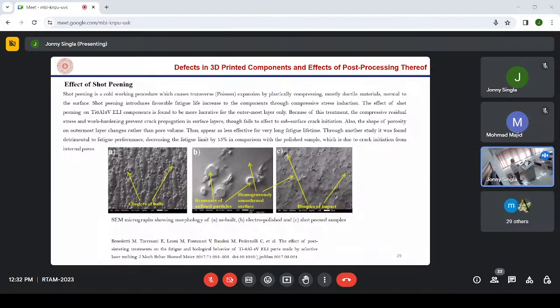In another study, it was found that it is detrimental to fatigue performance, decreasing the fatigue limit by 15% in comparison with the polished sample, which is due to crack initiation from the internal pores. So it is not certain that it is definitely going to improve the high cycle fatigue strength. Okay. So that means this treatment alone cannot be used as a post-processing technique.